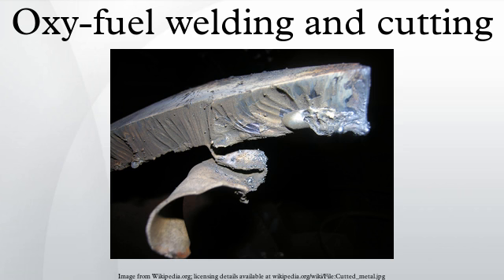In oxy-fuel cutting, oxidation of the metal being cut produces nearly all of the heat required to burn through the workpiece. Oxygen is usually produced elsewhere by distillation of liquefied air and shipped to the welding site in high-pressure vessels at a pressure of about 21,000 kilopascals. It is also shipped as a liquid in dewar-type vessels to places that use large amounts of oxygen. It is also possible to separate oxygen from air by passing the air, while under pressure, through a zeolite sieve which selectively absorbs the nitrogen and lets the oxygen pass. This gives a purity of oxygen of about 93%. This works well for brazing, however higher purity oxygen is necessary to produce a clean, slag-free kerf when cutting.